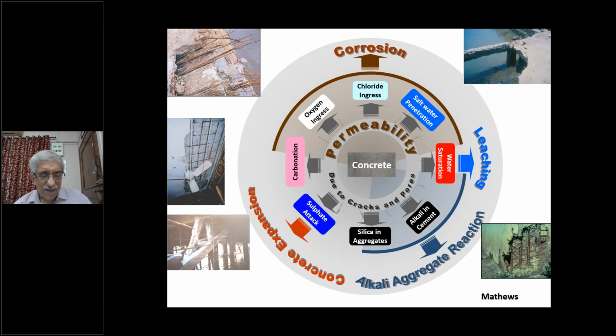Sulfate attack also can take place. Generally, the seawater contains chlorides and sulfates. Many a time people forget that chlorides are more harmful than the sulfates in the groundwater and subsoil. So one has to make sure that the sulfate attack is minimized, and the best way now known to engineers is to use the pozzolanic material, slag, or maybe fly ash from a thermal power station. But essentially, these materials have to be good and produced in the right way so that they can protect the concrete and avoid the expansion due to sulfate attack. Again, ettringite is produced, which causes expansion and cracks in concrete.